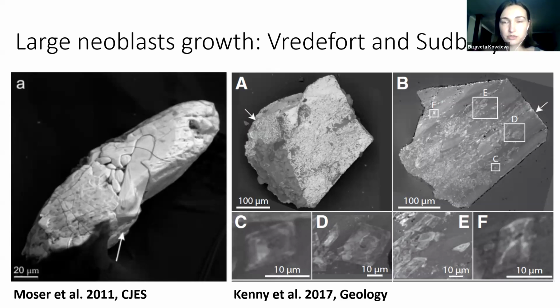They were dated and they represented the age of the impact event, which confirms that they formed as a result. And in the example on the right from Sudbury, you can see this large grain, something is in B, it's like a big mess, not really visible what's going on inside, but these little boxes zoom in on certain areas, and then you can see in these boxes nicely shaped, zoned crystals, which are growing inside this initial